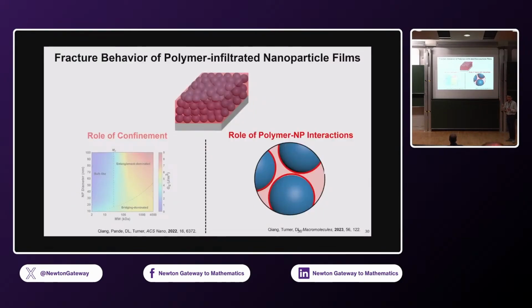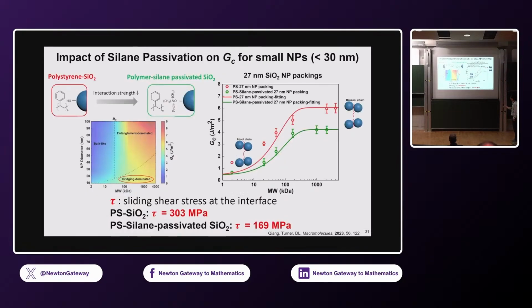So what if we change that interface now, right? The interactions between the polymer and the nanoparticle. And let's see what the effect is. All right, so for small particles, what we did here is we took silica and polystyrene, and to weaken those interactions, we passivated the silica surface with some silane groups, okay, so that the strength of interaction is much weaker. And for the small particle case, what we see is that toughness indeed does decrease. Okay, so that's what you see here.